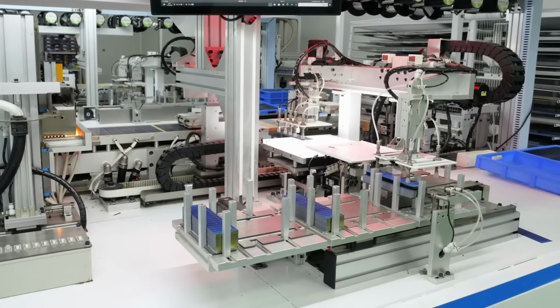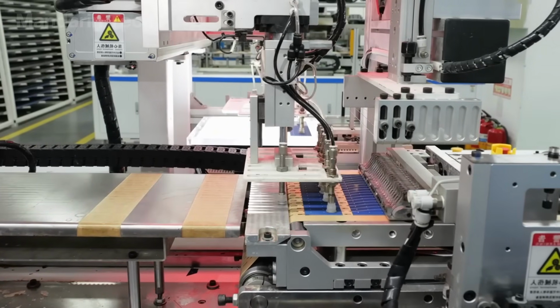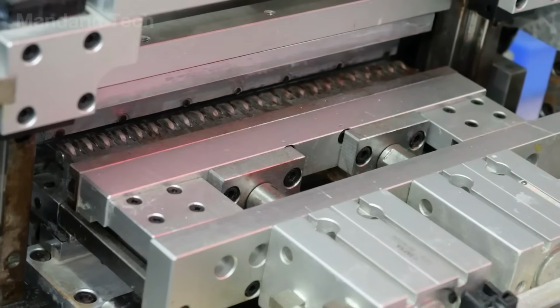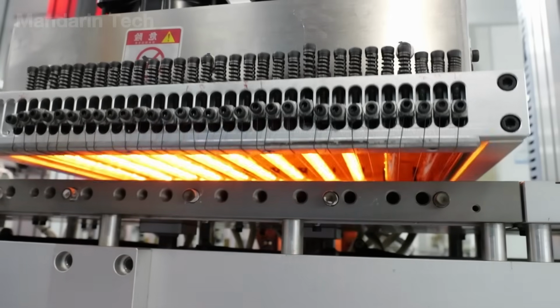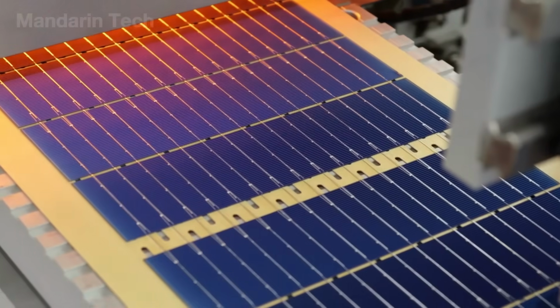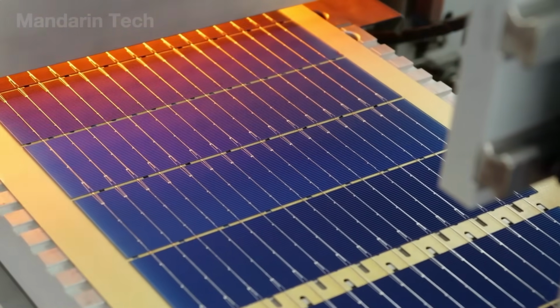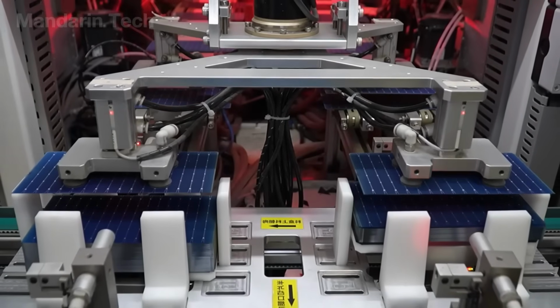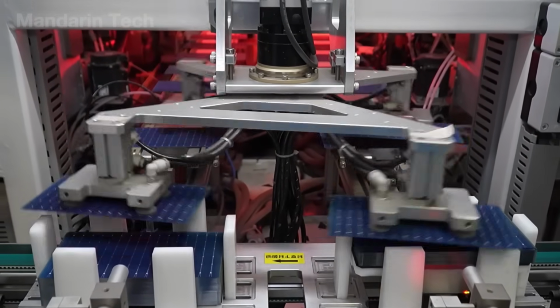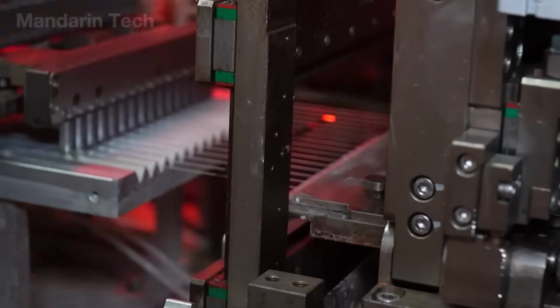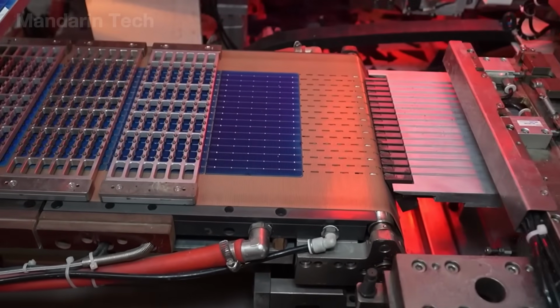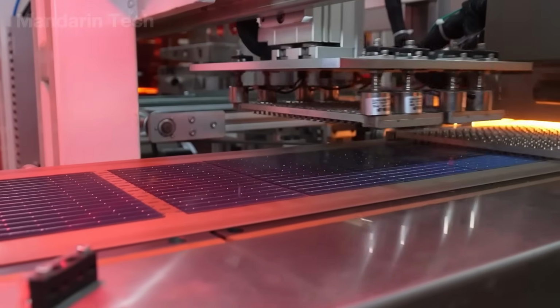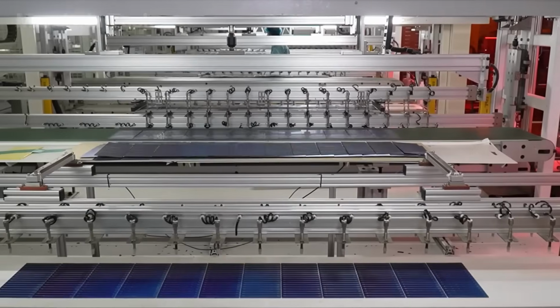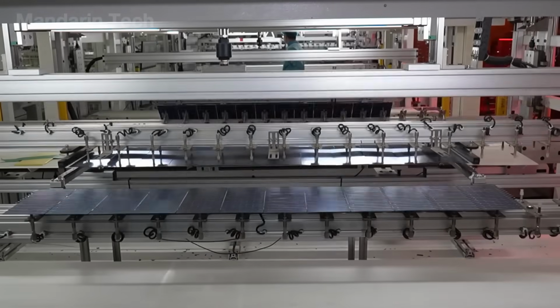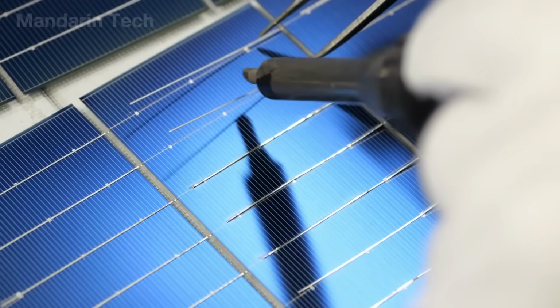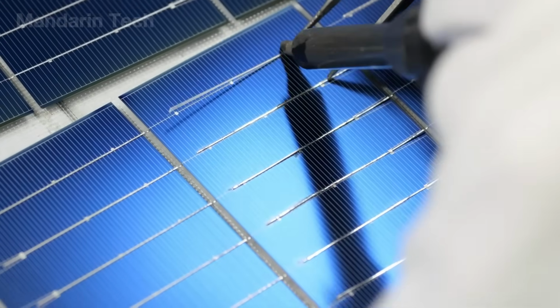After inspection, solar cells enter the most delicate stage, energy string welding. Inside the factory, robots pick up 0.2 millimeter thin cells and align them with less than 0.1 millimeter deviation. Automated arms use tin-coated copper wires heated to 250 degrees to connect the positive and negative poles, forming strings of 60 to 72 cells. Each joint is checked by infrared cameras to ensure smooth current flow. Even a tiny crack can cut efficiency by 5%.